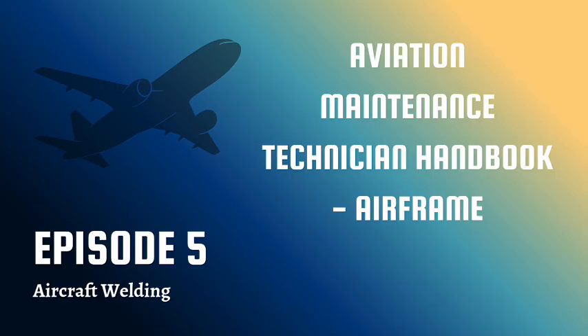If you go above 15 psi, you risk pulling acetylene gas out of the acetone solution faster than it can be replenished. You increase the concentration of unstable free acetylene gas in the regulator and hoses and dramatically increase the risk of detonation. 15 psi is the absolute limit. Memorize it. Okay. Oxygen, on the other hand, that's the safe gas in this pairing, right? Colorless, odorless, doesn't burn itself. It just acts as the accelerator.